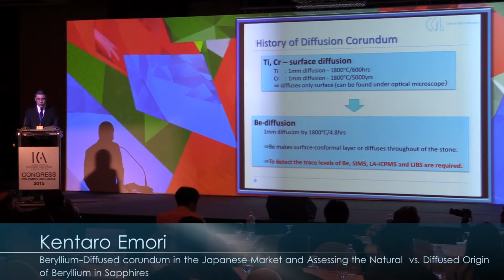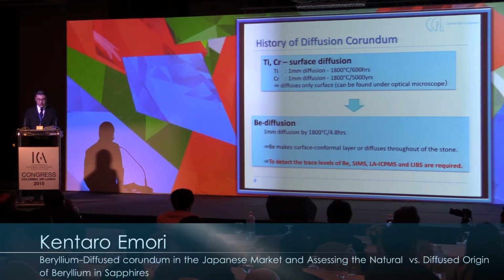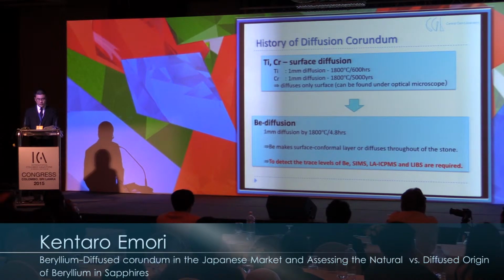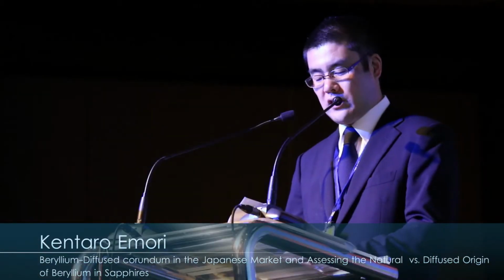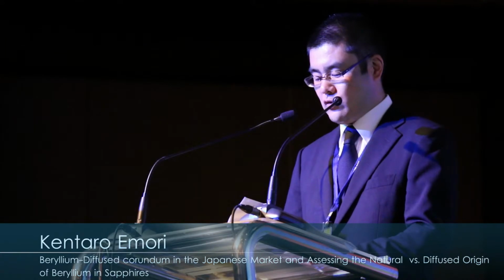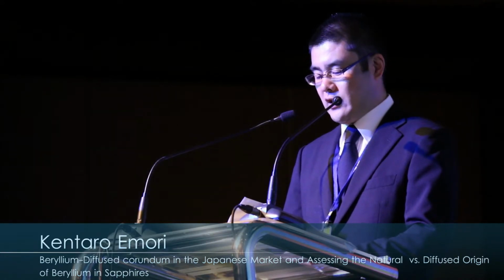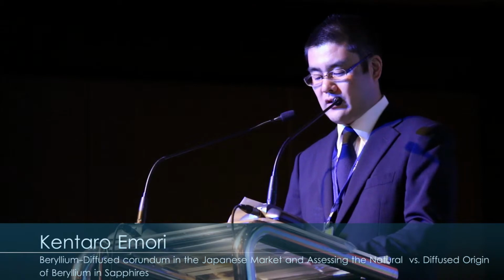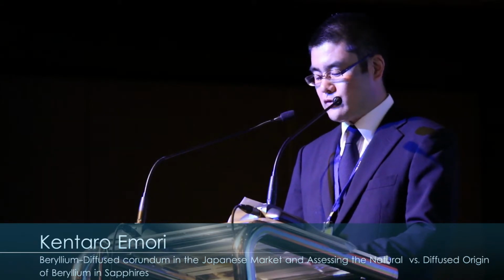The diffusion rate of beryllium is very high, and it takes 4.8 hours at 1800 degrees Celsius for 1 millimeter diffusion. Therefore, beryllium may produce a surface conformal layer or even diffuse throughout the stone. To detect the trace level of beryllium for identification of beryllium diffusion treatment, SIMS, LA-ICP-MS, and LIBS are required.